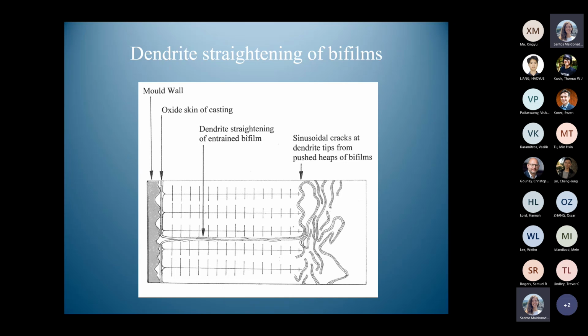I say push. This is a colloquialism used amongst researchers. What it means is this is trembling with a Brownian motion against the tip of the dendrite. So every time it moves away, more liquid can come in, and so it looks like the interface is being pushed. In fact, as it moves away, liquid can access and freeze, and so it's a one-way process. So it's very convincing as a pushing action. But anyway, as our dendrites start to grow and they push, they slowly push, and they slowly flatten out the bifilm. So we get our engineering crack back again, and properties now really fall a long way as a result.